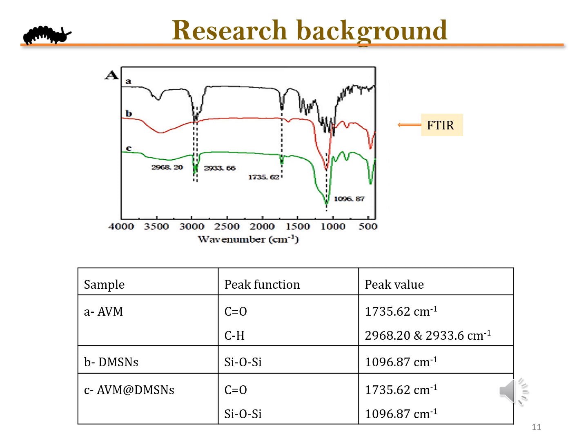FTIR, that is Fourier transform infrared spectroscopy, was performed to detect the functional groups present on the synthesized material. Spectrum A, which is of the drug, shows a peak at 1735 of carbonyl and a peak of alkyl at 2968 cm inverse, whereas the nanoparticles show a peak at 1096, which is of the silicate framework. Similarly, the drug-loaded nanoparticles show peaks of both the drug as well as the carrier material, that is the carbonyl group at 1735 cm inverse and the silicate group at